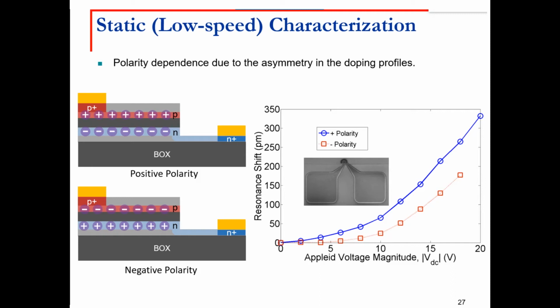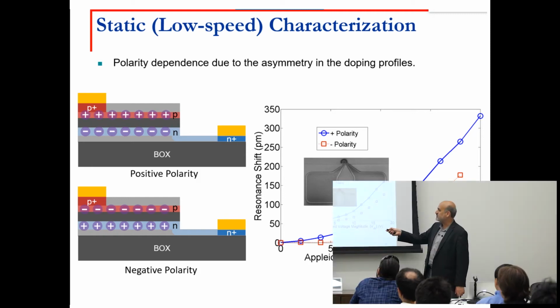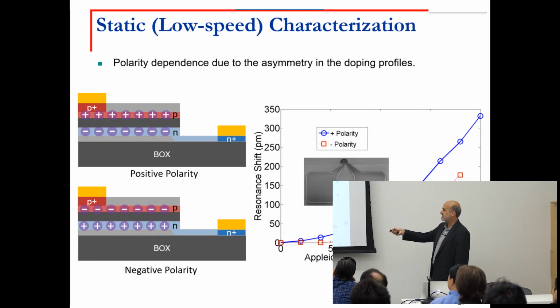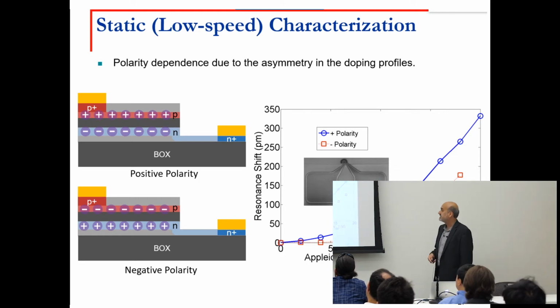This is the actual device under DC, so you can tell that by applying a voltage, you accumulate the charges, but you want your charges to be electrons and holes, not donors and acceptors. So you have to pick the correct polarity. If this is p-type, this should be p, this should be n, positive and negative. This is holes, this is electrons, and that's why you will get a better sensitivity compared to the case where you apply the voltage in the reverse direction where some of the donors and acceptors help you. But that's just trivial things in this type of structures.